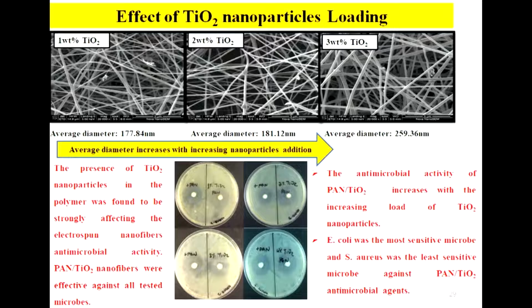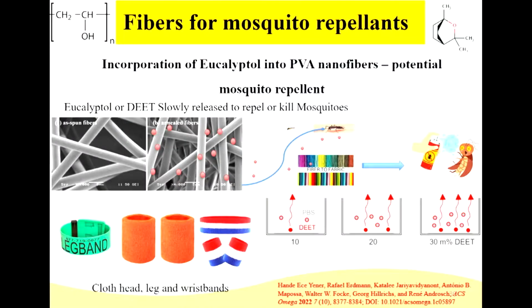And you find that actually E. coli shows the most activity against the nanofibers embedded with nanoparticles, as compared to perhaps Staphylococcus aureus. One of the things that we are currently doing, and this is work with collaborators from the Maasai Mara University in Kenya, since there are a lot of problems with malaria in the region, was to see if we can embed some, not nanomaterials this time, but some mosquito repellent materials into the polymer fiber so that we can explore their slow release into the environment.